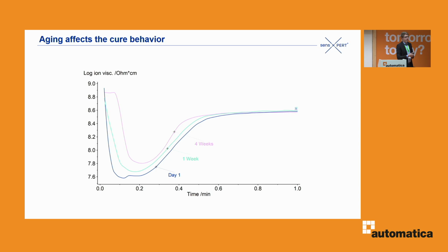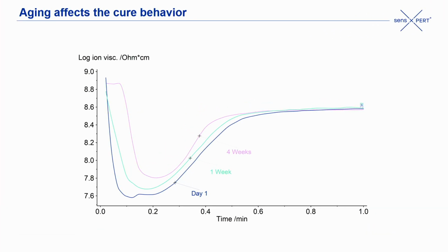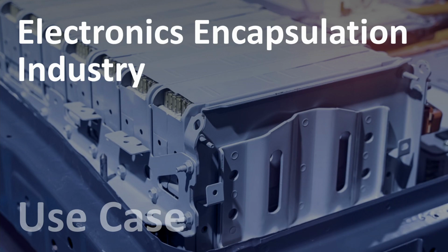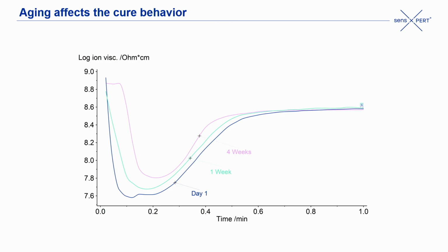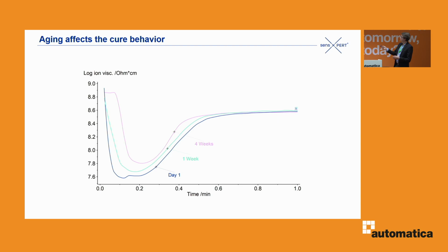And I mentioned storage before. This material is aging, even if you have not used it in production before. So if we take a fresh bag of material and do an experiment with it, we see the curve here, day one. We do the exact same production cycle one week later, and we have a different behavior, right? The reaction happens faster. Four weeks later, even faster. That's because the material is already starting to react very slowly, but it's happening.